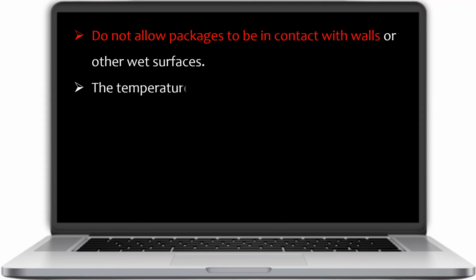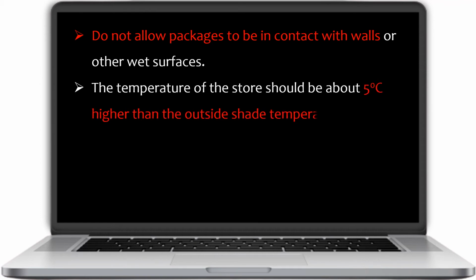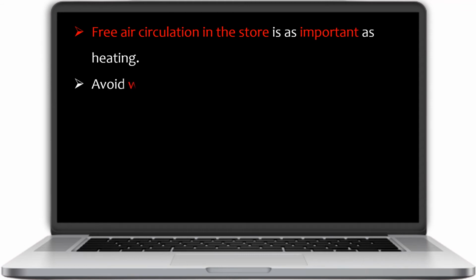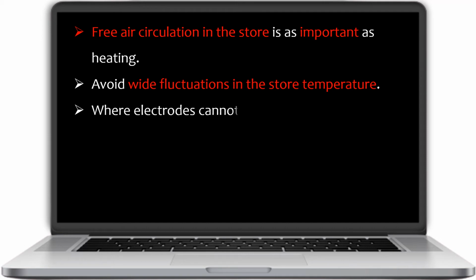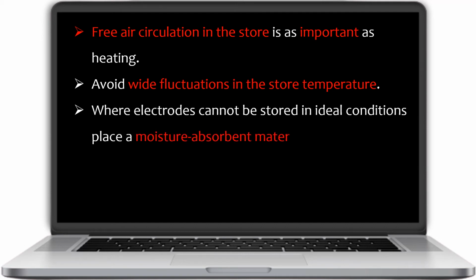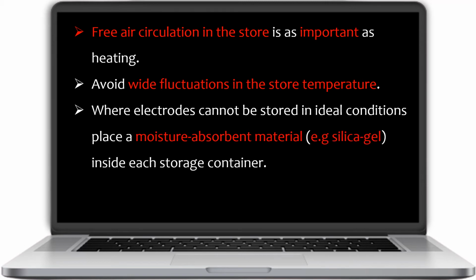The temperature of the store should be about 5 degrees Celsius higher than the outside shade temperature to prevent condensation of moisture. Free air circulation in the store is as important as heating. Avoid wide fluctuations in the store temperature. Where electrodes cannot be stored in ideal conditions, place a moisture-absorbent material, for example silica gel, inside each storage container.